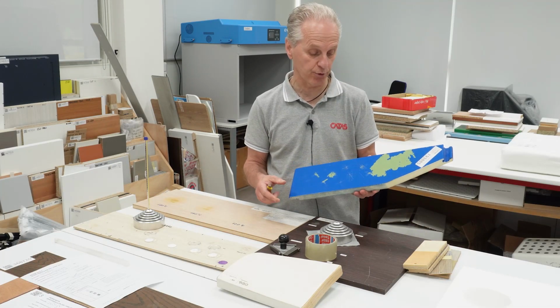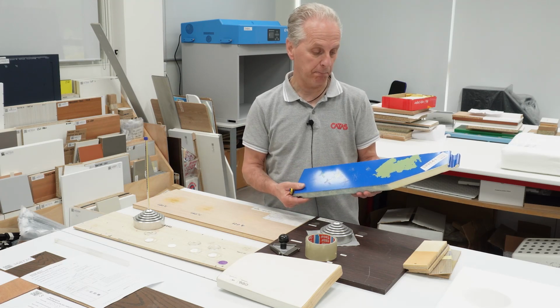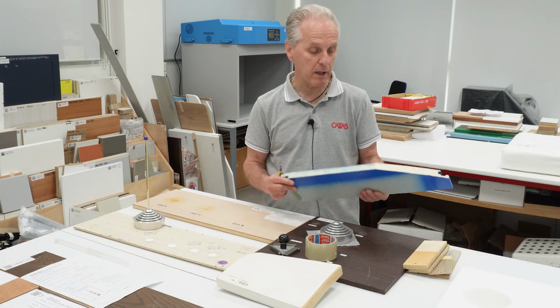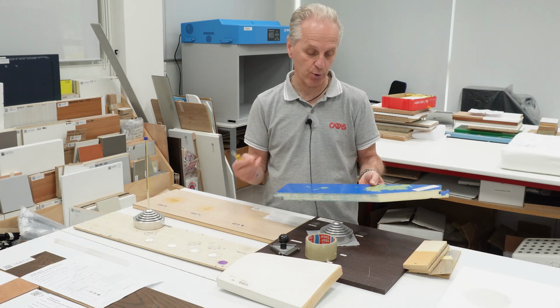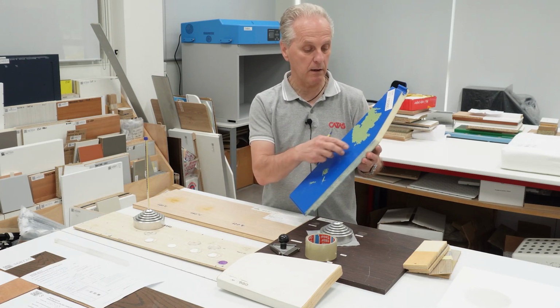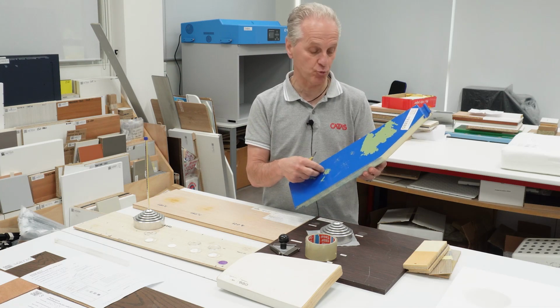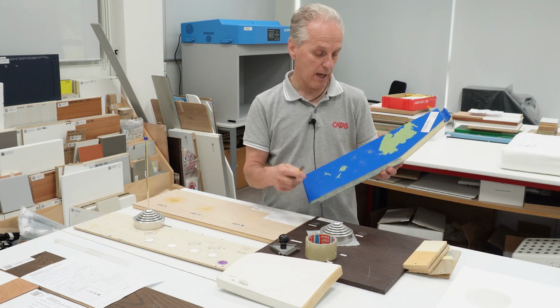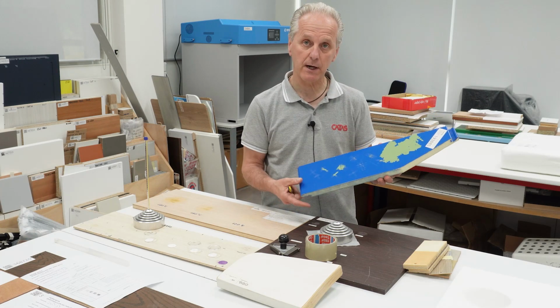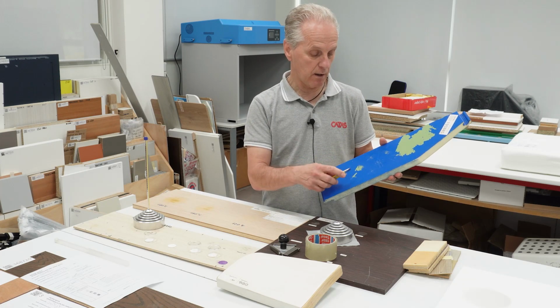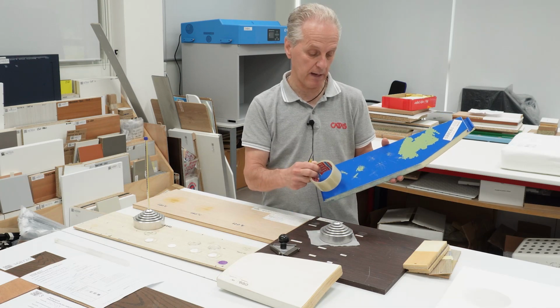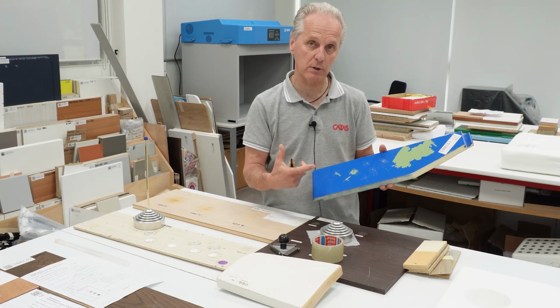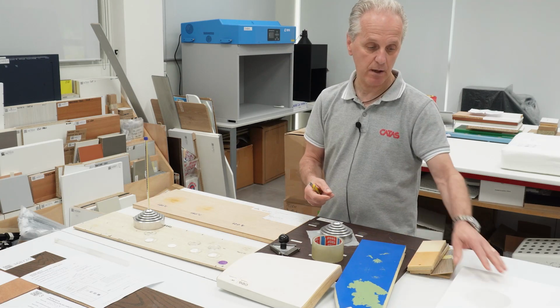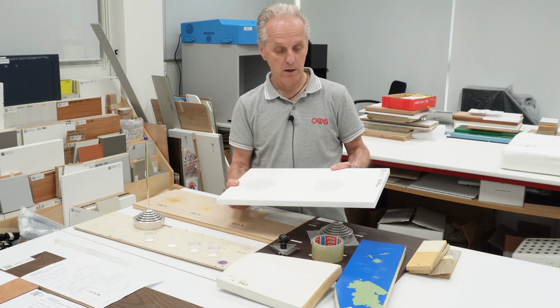Other characteristics that are commonly requested to be tested refer to the varnish coating adhesion to a surface. Oftentimes, due to problems with the varnishing line, the product or the process itself, the varnish coating is not adequately adherent to the surface. Here at CATAS, we run pull-off tests for surface adhesion according to international methodology. We etch the varnish film and then we pull it off with an adhesive tape, and finally we evaluate the quantity of removed varnish.